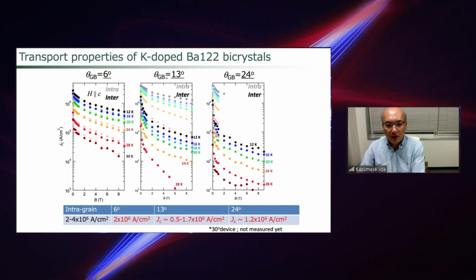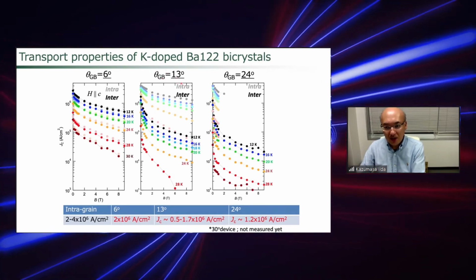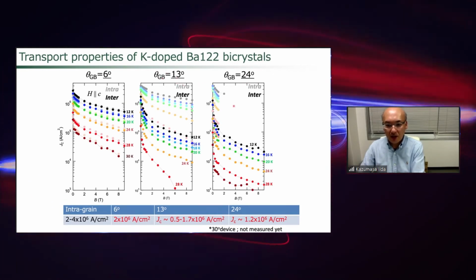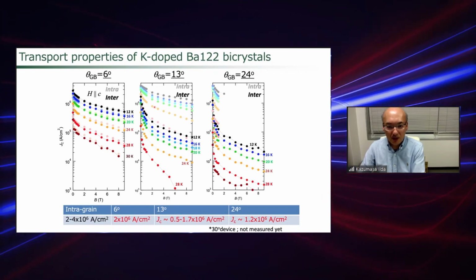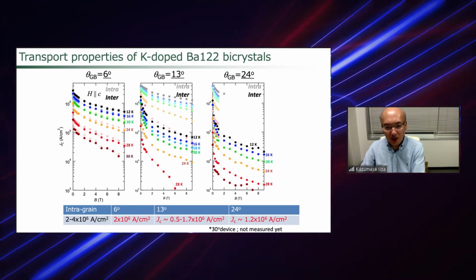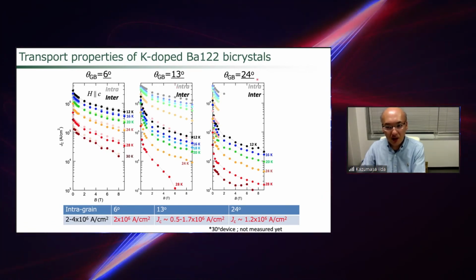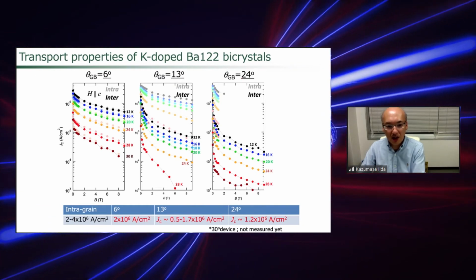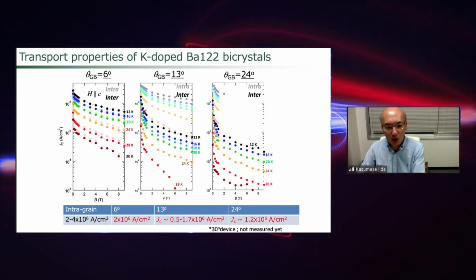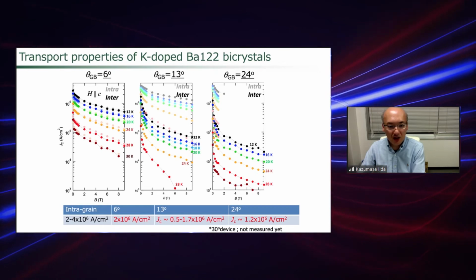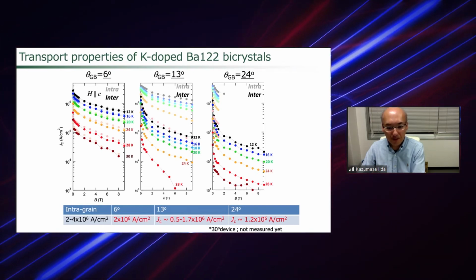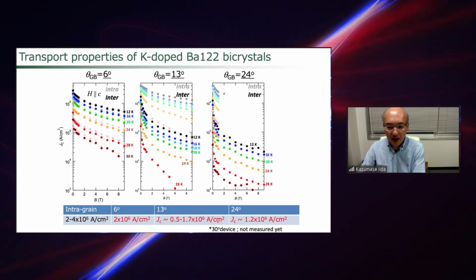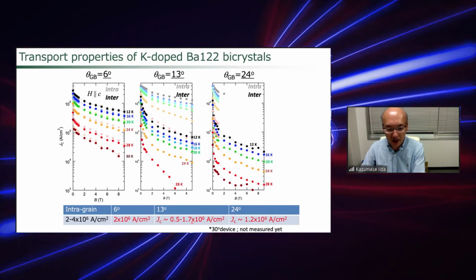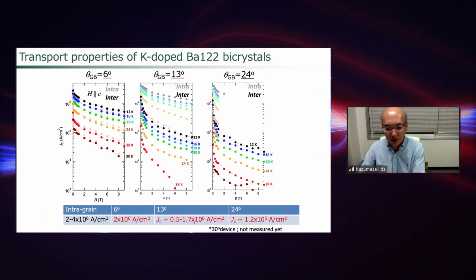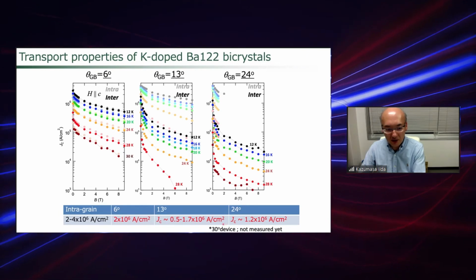And we also plot the 13 degree and 24 degree samples, but unfortunately, we observed weak-link behavior for the 13 degree and the 24 degree. As you can see, even in a small magnetic field, Jc is dropped significantly. But nevertheless, the Jc is quite high and maintained over 1 mega ampere per square centimeter.